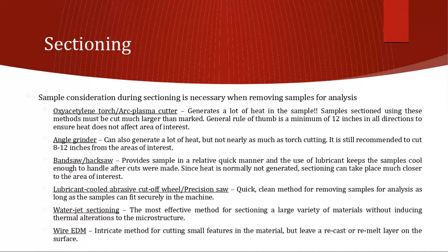The next method for sectioning, wire EDM. This particular one, you can cut very small, intricate features into the material. It does leave a slight recast or remelt layer on the surface. So during any type of metallographic preparation, you just have to make sure that you grind through enough of that to reveal the true microstructure, not the recast or remelted microstructure.